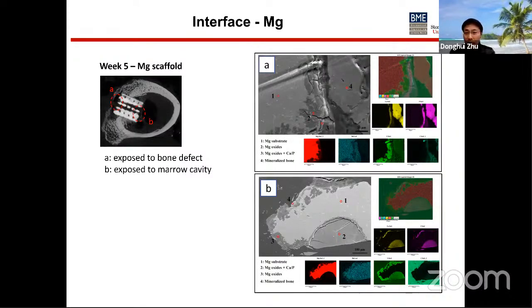This is 5 weeks after implantation of the magnesium scaffold. We look at two regions, A and B. A is exposed to the bone defect, while B is exposed to the marrow cavity. The interface is checked by SEM EDS.